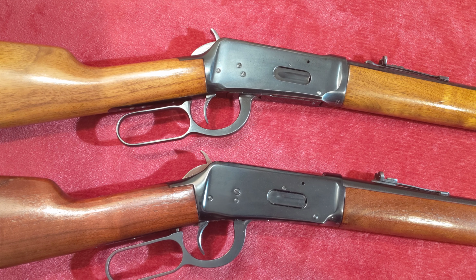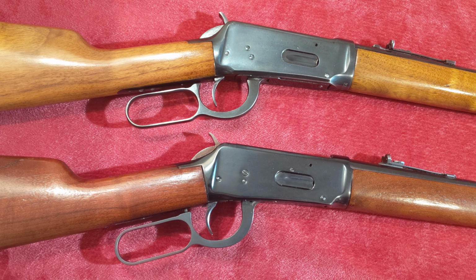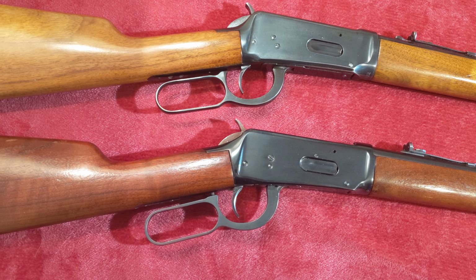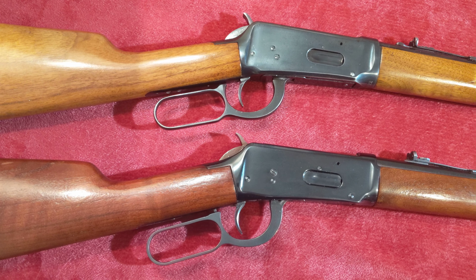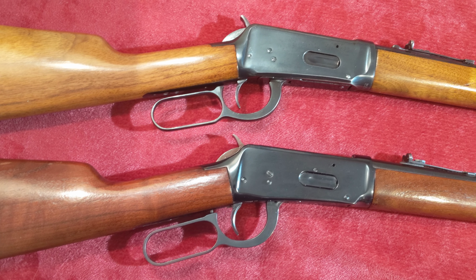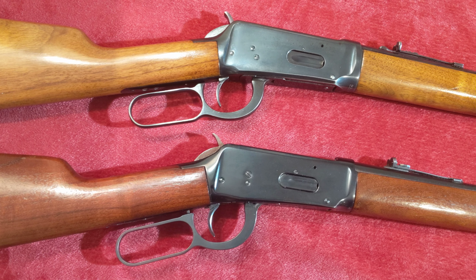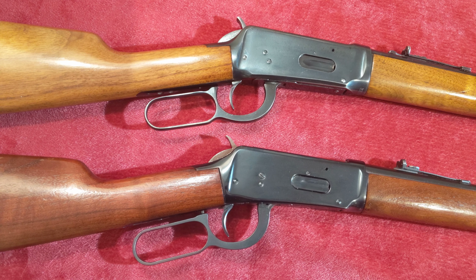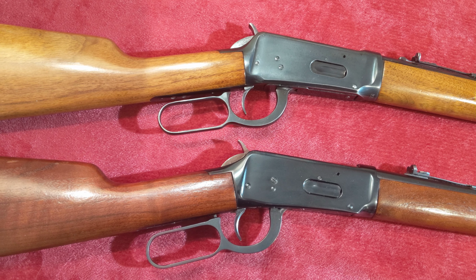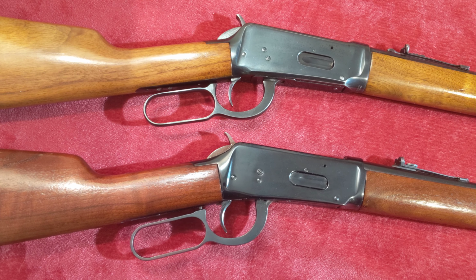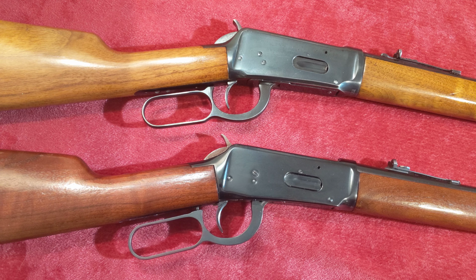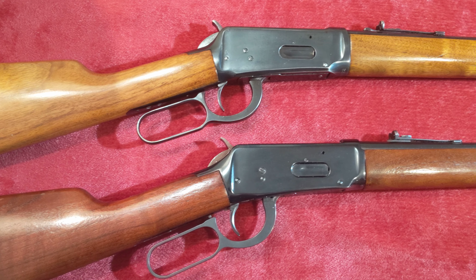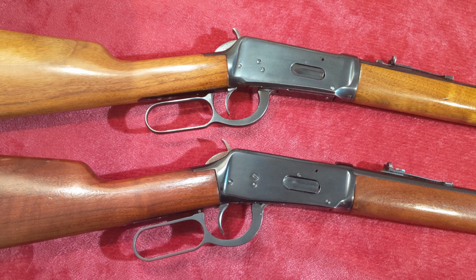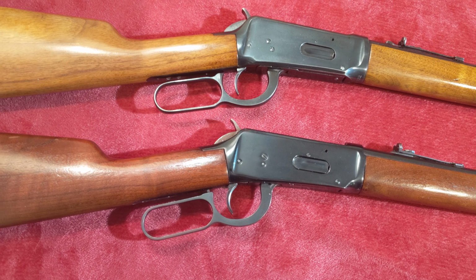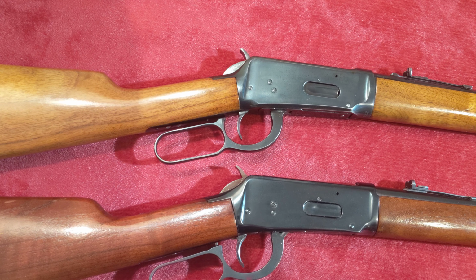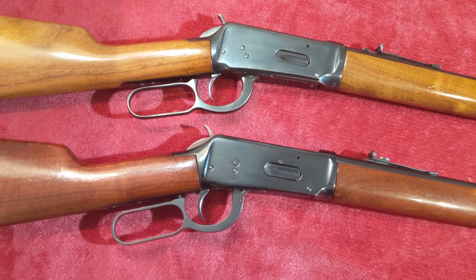So after 1964, there were a couple of different processes that were used. 64 to 68, it was a Dulite 3-0 process. In 1968, they went to what's called a black chrome plating. It seems like kind of a mixture of two terminologies, but that's what they were calling it. And then in 1972, beginning with serial number 3,800,000, somewhere in that area, to 1981, Winchester revised the process again. What they were doing at that point was basically plating the receivers with iron. So they iron plated the receivers, and then they went back to the old original oxy black bluing process once the receivers were iron plated.